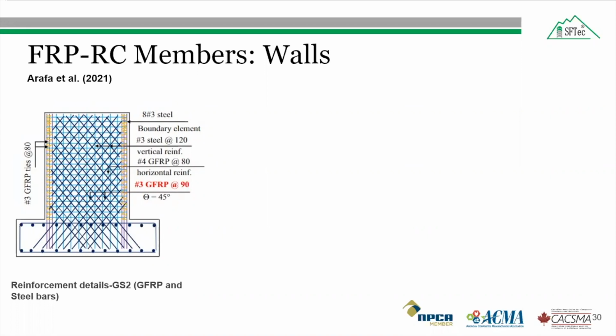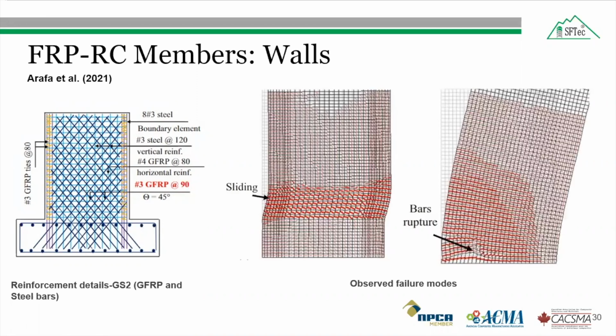and validated based on the previous results on GFRP reinforced concrete walls. The specimens were representative of bridge pier walls in the strong direction. The bidiagonal web reinforcement, as you can see here, was glass fiber reinforced polymer bar, and all the main reinforcement, the vertical bars, were steel bars. Only these horizontal bars and the ties for the boundary element were GFRP bars. The finite element analysis provided accurate simulation of the experimental response of the tested steel and glass fiber reinforced polymer concrete bridge pier walls.